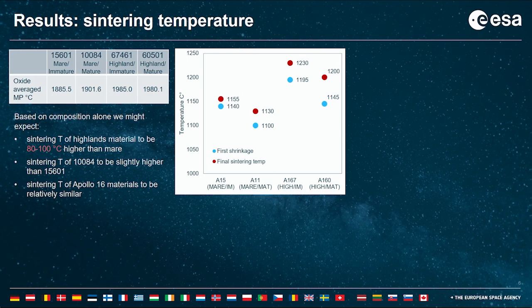And so, as we can see here, the composition pretty reasonably predicts the difference between Mare and Highland material, that on average the Highland material did sinter at a higher temperature than the Mare material. However, the other two predictions that we could make based on composition don't hold up at all. So the Apollo 11, as it would be predicted to be slightly higher based on the composition, actually sintered at quite a lower temperature. By the time that it was very well sintered, the Apollo 11 sample wasn't even shrunken away from the walls or removable from the crucible.